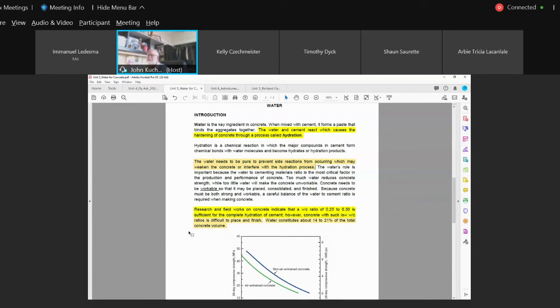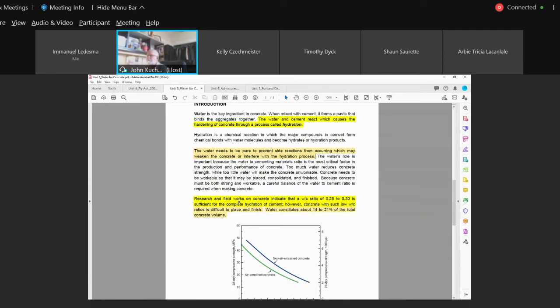So again, it's like anything else. What is the source of his raw materials? And in this case, the water. Get it tested. You never know what's in it. Maybe there's high algae in it. pH could be different. Research and field works on concrete indicate a water cement ratio of about 0.25 to 0.3.